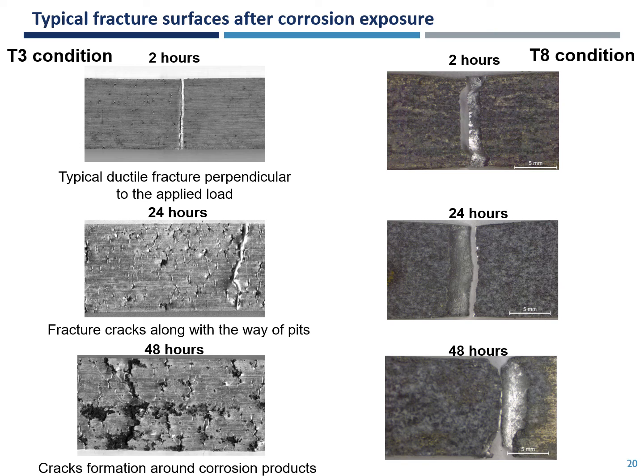Significant differences are also evident for the typical fracture surfaces after corrosion exposure times between the T3 condition and T8 condition of aluminum alloy 2198. For instance, for the T3 condition, a localized corrosion morphology is evident, while for the T8 condition, the corrosion morphology seems to be more uniformly distributed to the whole surface, probably due to the distribution of the precipitates. Additionally, no significant difference between the different corrosion exposure times is evident in the T8 condition, while in the T3 condition, the differences in the corrosion morphology between the different corrosion exposure times is evident.